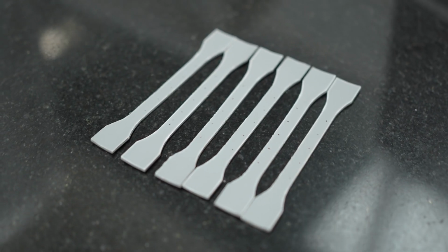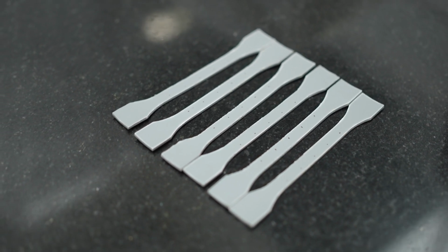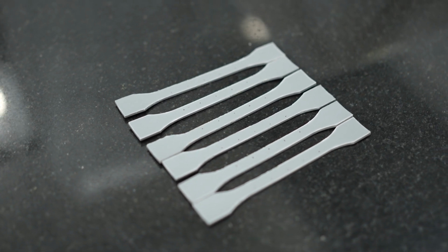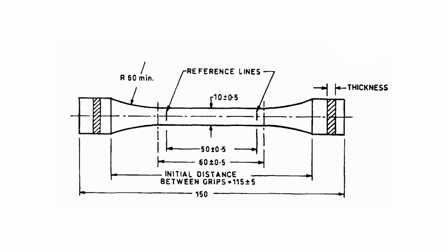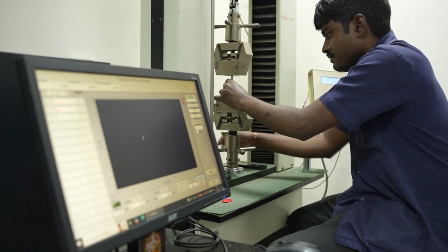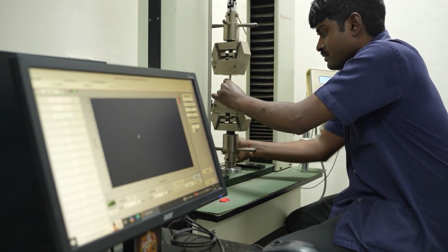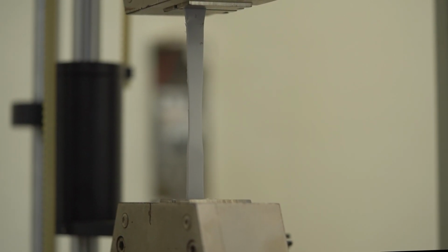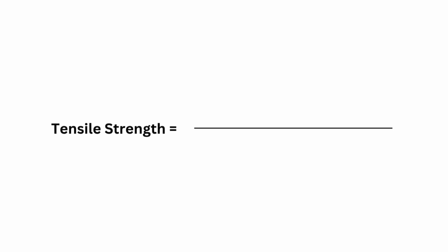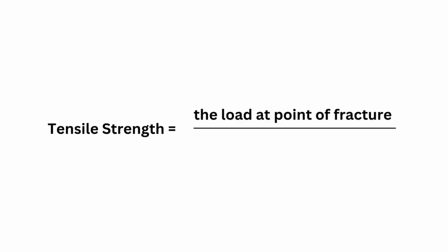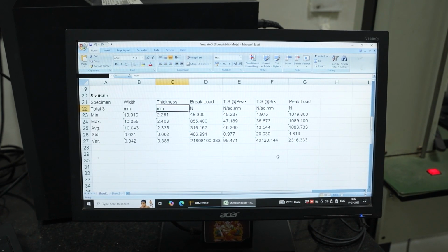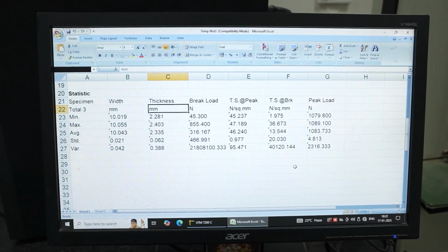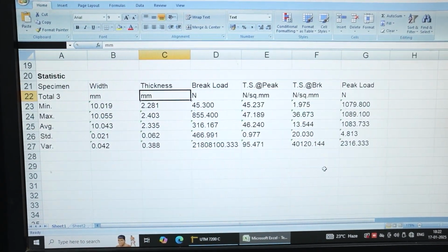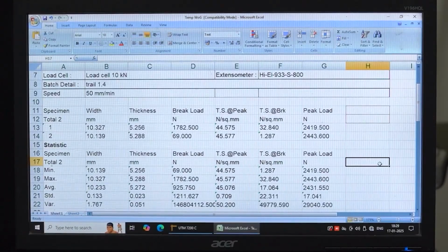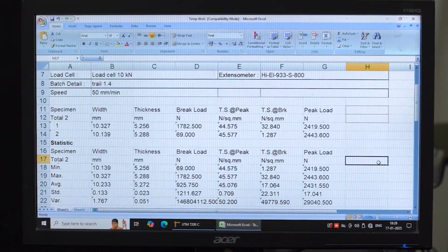For the test, specimens of dumbbell-shaped cut or machined from the lengths of pipe in the longitudinal directions having dimension as shown on image. After that, the test specimen is mounted on the jaws of the machine and the load is applied uniformly till the time of fracture. Tensile strength is calculated by dividing the load at the point of fracture by the original cross-sectional area. The test is conducted on 5 specimens and an average of 5 is taken for calculating tensile strength. Tensile strength should not be less than 45 megapascal.